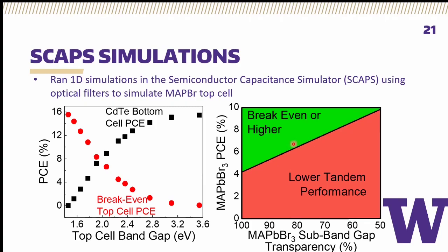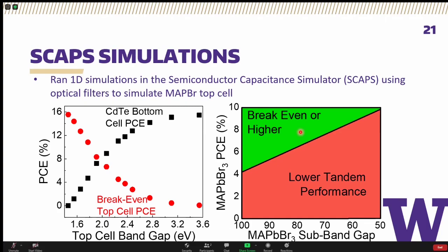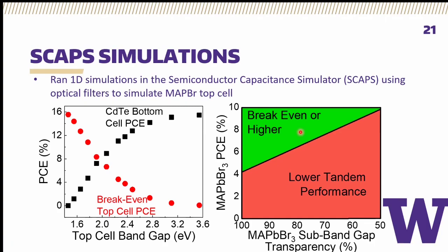And if you can find a way to smooth the micron scale morphology out of the MAPbBr, you can get to a regime where you have a wider window of efficiency improvement, but even so, you need about 6-7% really good efficiencies to even think about improving the efficiency of the tandem. And then you have to consider the economic consideration, which is, can we make this so much more efficient that the additional cost of making the MAPbBr solar cell is worth it? Do we get more electrons out to justify the cost? And that becomes a bit of a hairy proposition, especially in a 4-terminal.